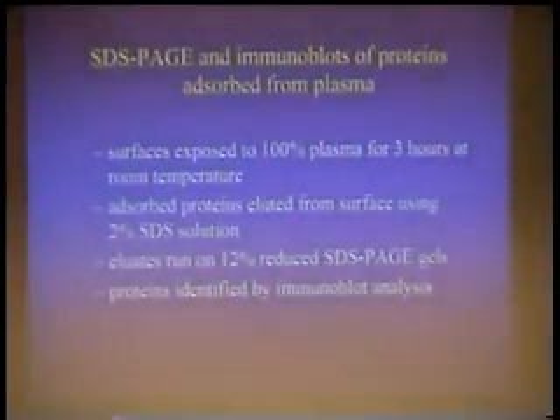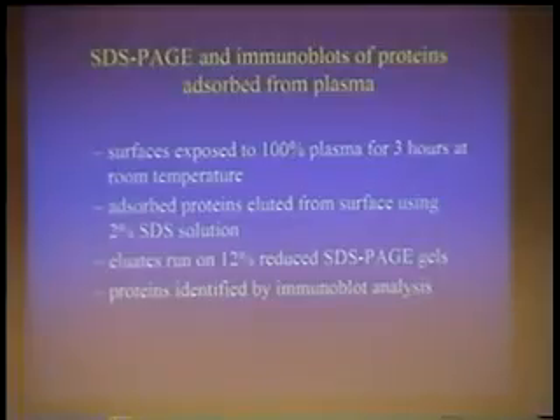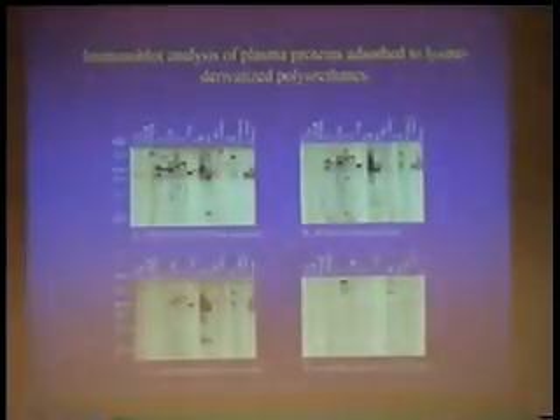When we're up at this density here and 100% plasma, we have a monolayer of plasminogen on there, based on this number, which suggests that maybe we've got plasminogen and very little else on that surface, which is great. But we can show that, in fact, to be the case by exposure to plasma, elution with SDS, and then running gels and immunoblots. Here's some data from that. I won't go into the details on this.